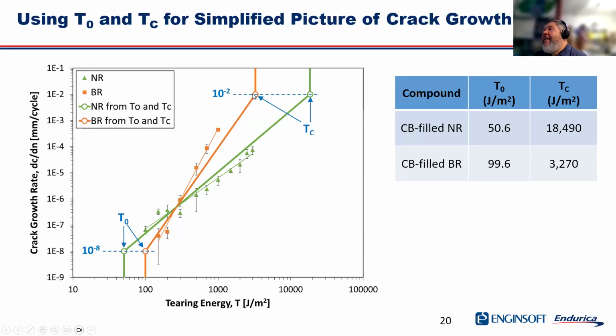And if you just draw a line connecting these 2 points, you can see that it actually reasonably approximates the crack growth rate curve for these two materials. So it's not exactly precise. The slope that you would get with this simpler method isn't exactly the same as what you get with the actual crack growth test, but it's in the ballpark. Which, when you're sorting material selection options and you've got a lot of them, this can be a very efficient way to rank order your materials.